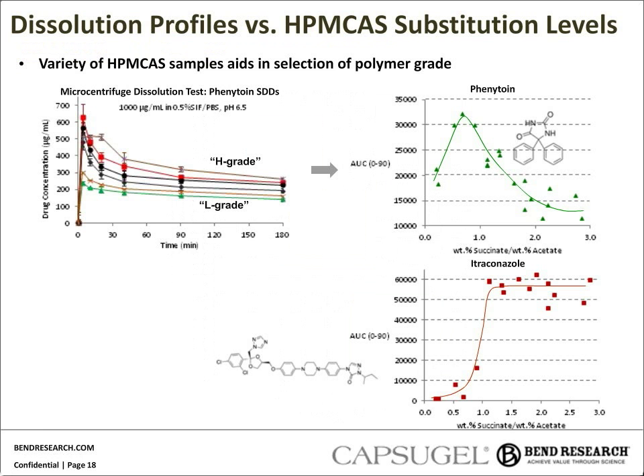For example, a model compound is shown here with various substitution amounts of HPMCAS, with the microcentrifuge data shown in the top left. As we change the polymer substitution amounts and ratios, we see the technical challenge of rapid dissolution with precipitation inhibition for this drug. We take the data from the left and translate it into the right, where now we're identifying that something with a succinate to acetate ratio of less than 1 is better for this drug than something with a more hydrophilic balance, something with a higher ratio.